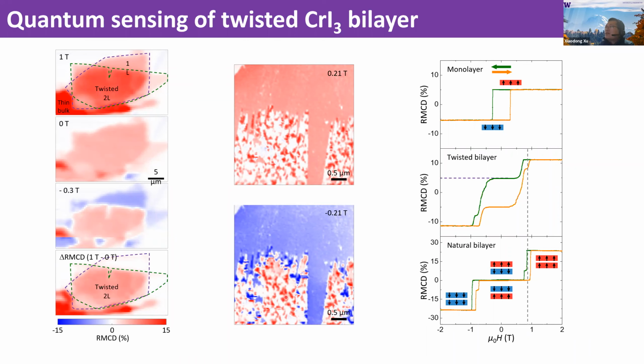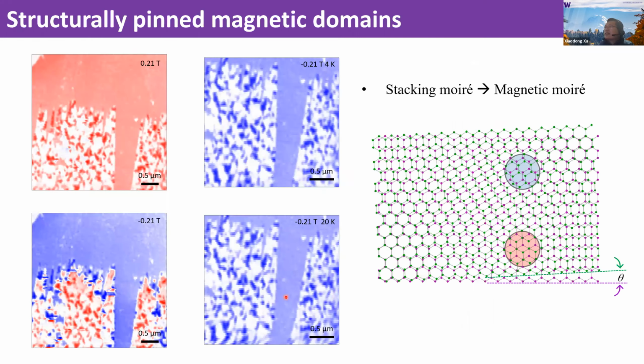And even though the pattern looks disordered, it's actually pinned by the local structures in these Moiré patterns, because I told you the interlayer coupling, whether it's ferromagnetic or antiferromagnetic, depends on local stacking orders. So once the sample is fabricated, the structure is determined, then the magnetization pattern is fixed. We cannot change the pattern. It's basically locked. It doesn't depend on the field or temperature, etc.